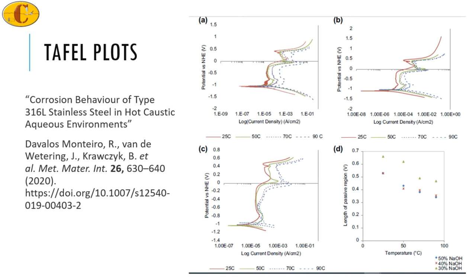Now in this case you will observe that this is the passive region. As I said, the passive region in stainless steel is the chromium oxide film, and the passive region means that you have a good chromium oxide film at this potential. Now at 0.5 potential, we found that the chromium oxide film was intact in the Pourbaix diagram. This is what we see over here.